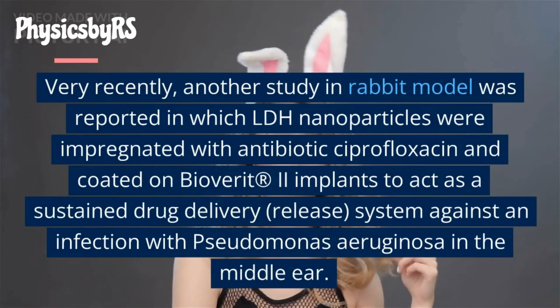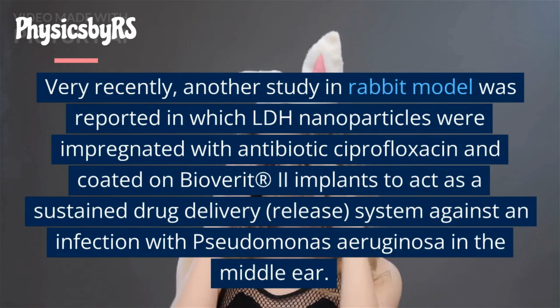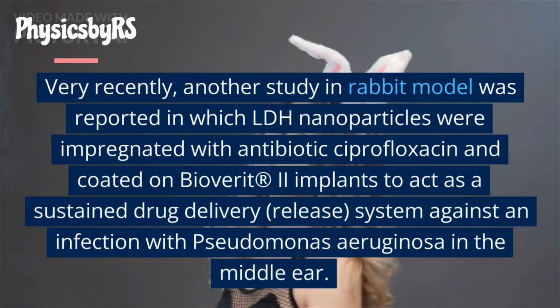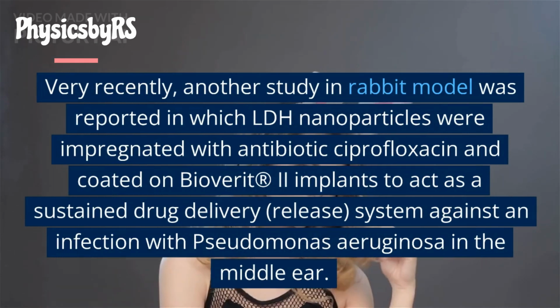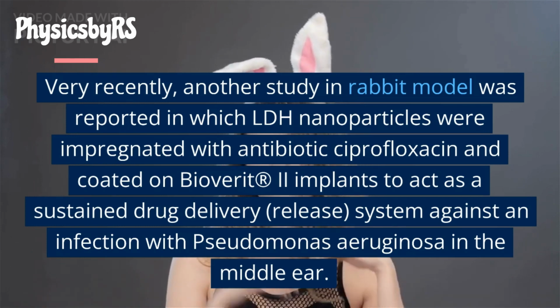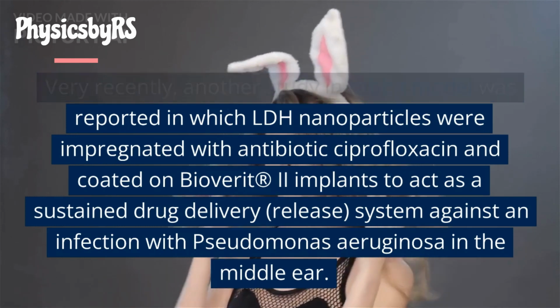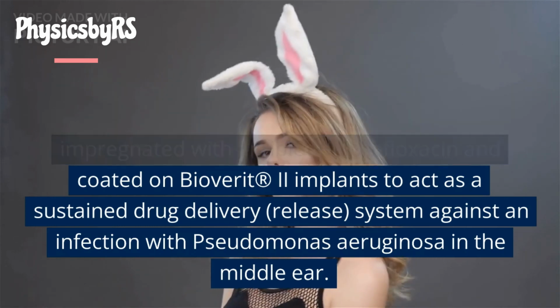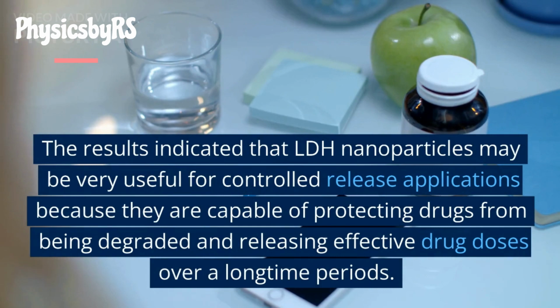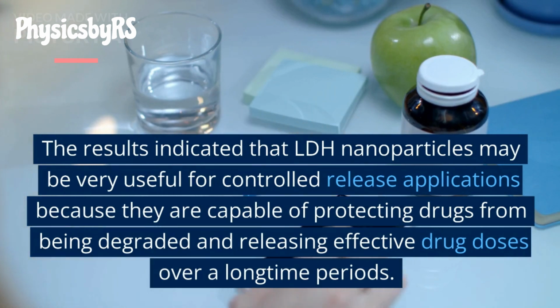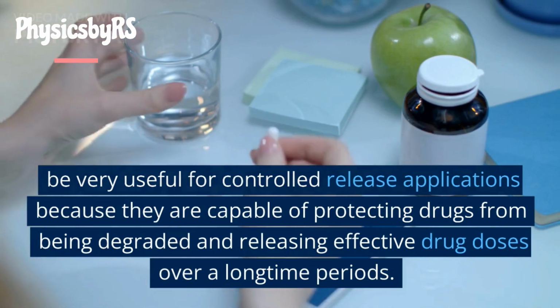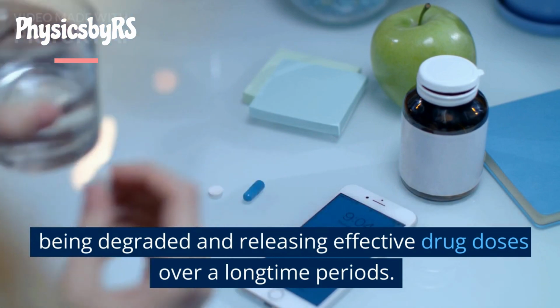Very recently, another study in rabbit model was reported in which LDH nanoparticles were impregnated with antibiotic ciprofloxacin and coated on BioVerit-2 implants to act as a sustained drug delivery release system against an infection with Pseudomonas aeruginosa in the middle ear. The results indicated that LDH nanoparticles may be very useful for controlled release applications because they are capable of protecting drugs from being degraded and releasing effective drug doses over a long time period.